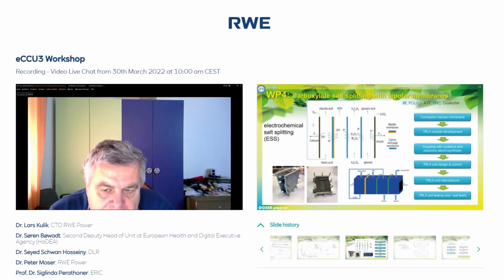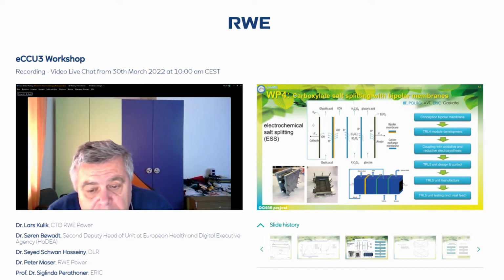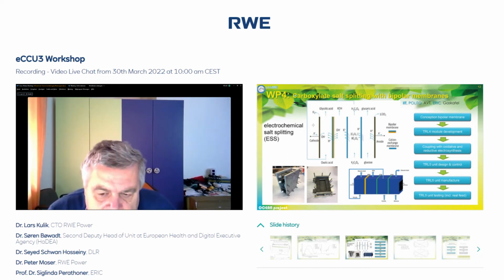We have also worked on carboxylated salt splitting. This is a technology that I think is quite common, because often in electrochemistry you form the salt due to the electrolyte, and then you need to convert it to the acid, and this can be done by electrochemistry. We give you a system which is much more integrated. Bipolar membranes are used here. We have developed the system up to TRL5. You see some pictures of the system, a very compact design and definitely much better than other possibilities.